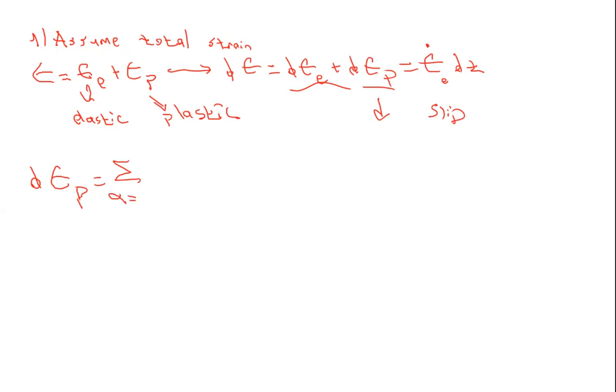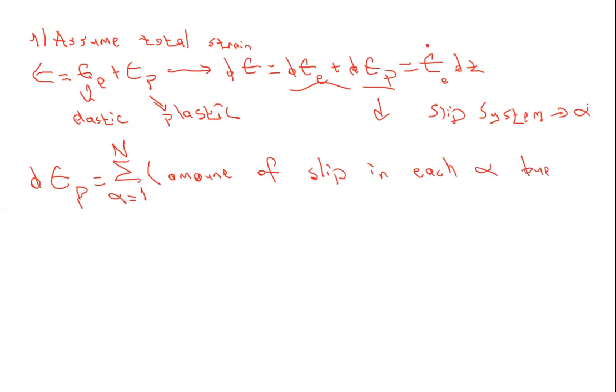Let's define alpha as a slip system. You know, in FCC, we have 12 slip systems. In BCC, we have 48 slip systems. We already know it. So for each slip system, from 1 to n, whatever we have, we just need to sum the amount of slip in each slip system, right? Due to the dislocation glide. So this is the amount of slip in each slip system alpha due to dislocation glide.